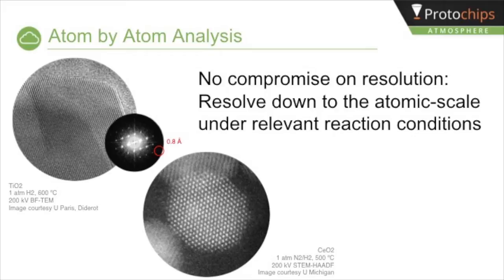Similarly, atomic resolution STEM images are routine, as shown in the right image, where a cerium dioxide nanoparticle is displayed with a resolution of 1.3 angstroms. This was taken at 1 atm of 95/5% nitrogen-hydrogen at 500 degrees Celsius.